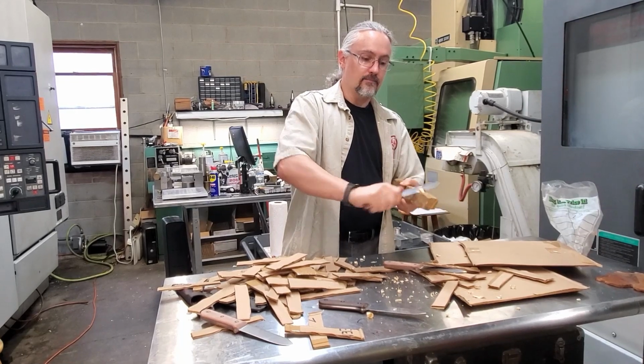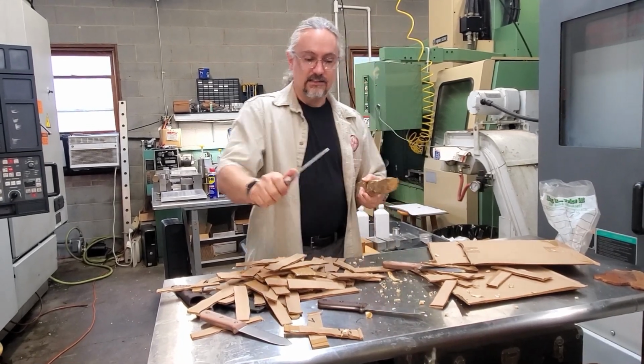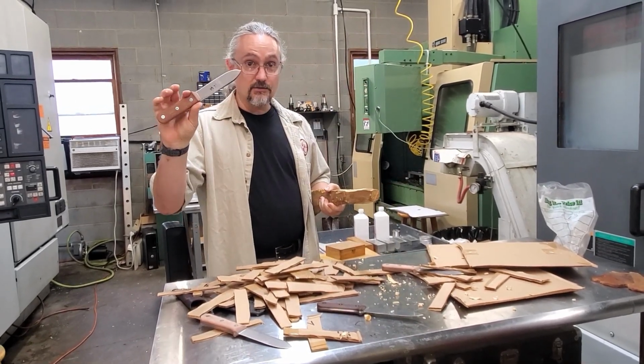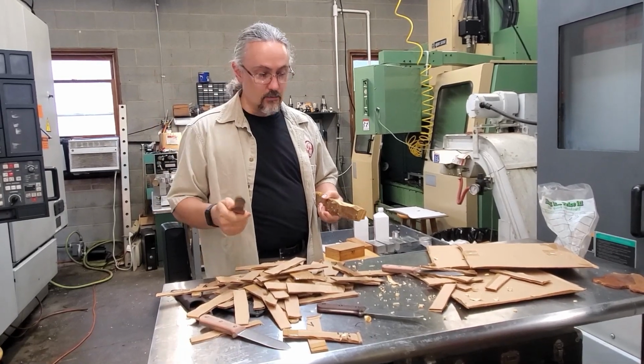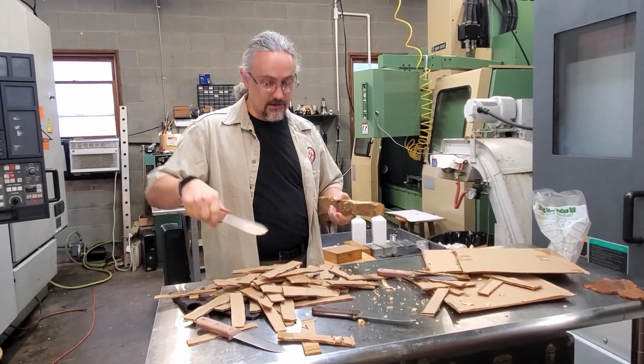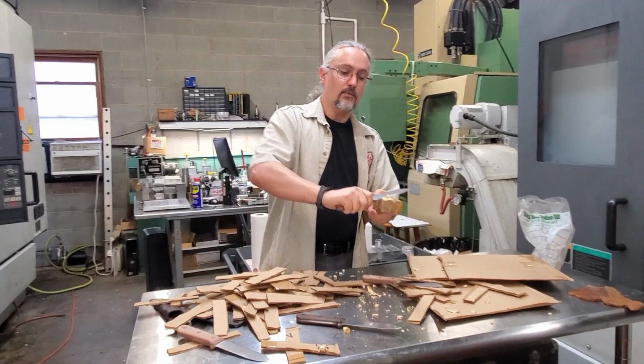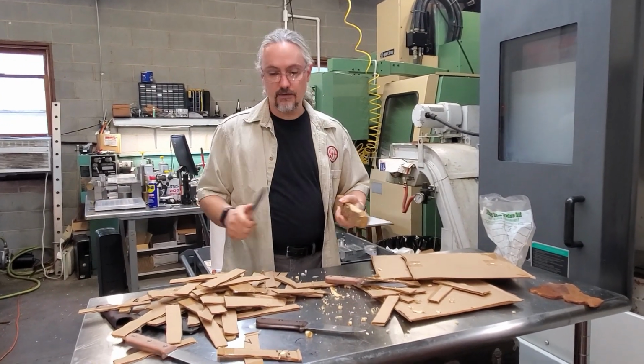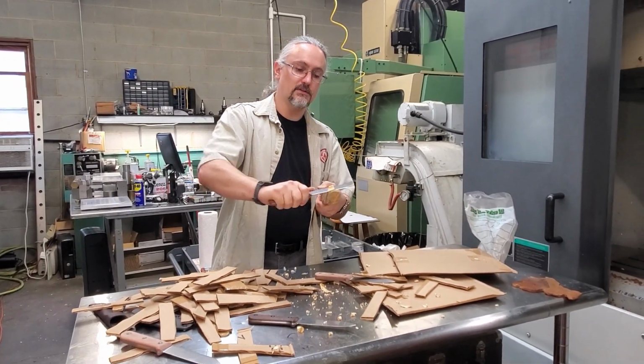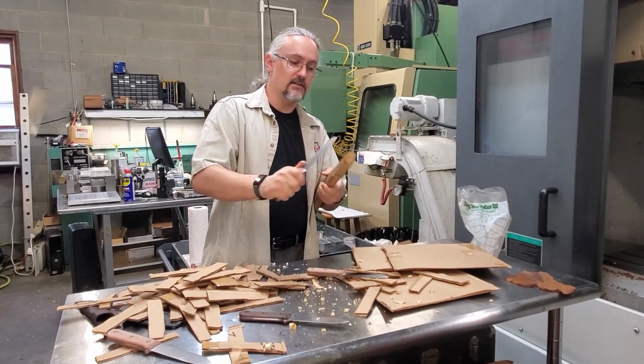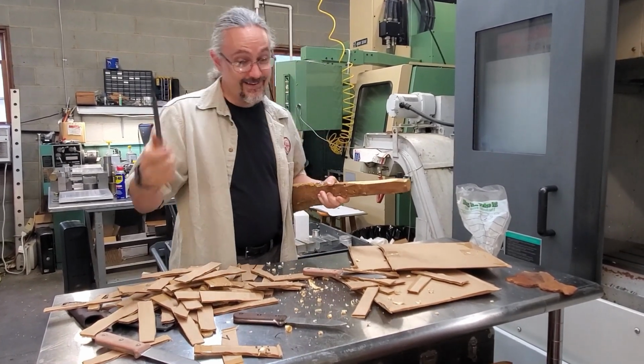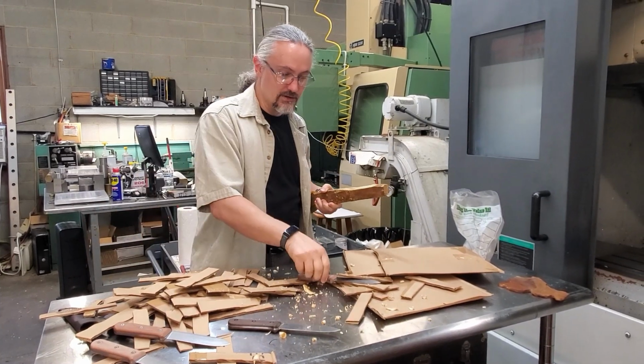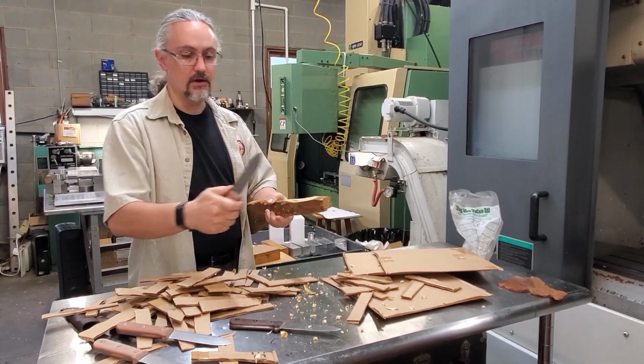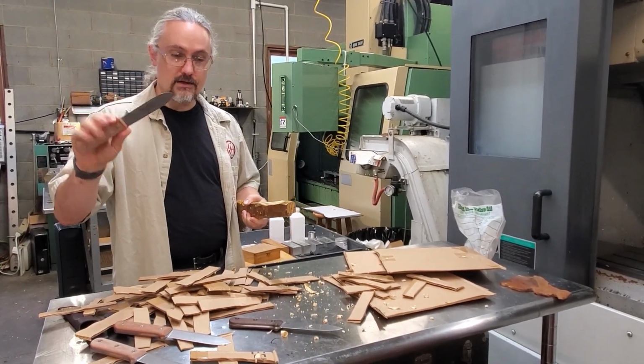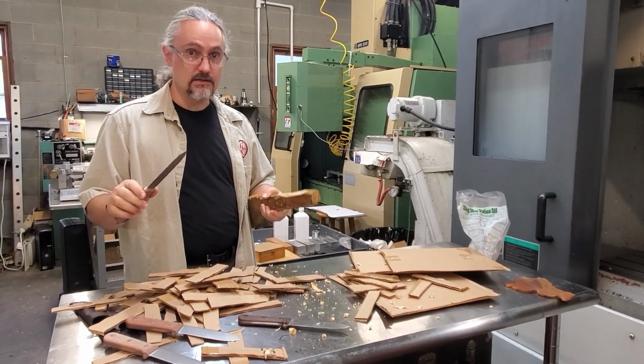Now that's ironic, because you would think something that takes as long as 3V to sharpen compared to AEBL would stay sharp longer, and it does in cardboard. But what we found, and this is the reason we developed the low temp cleats in the first place, is that in this kind of application, it doesn't really do any better than simple steels. It needed some work.